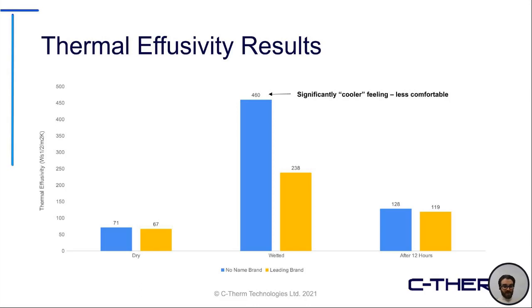So you can see in the dried state on the left side there, initially, very minimal difference, kind of a 4 effusivity point difference between the two materials. If we use that example that we showed earlier, you could essentially say there's no significant feeling of difference between those two materials in the dried state.